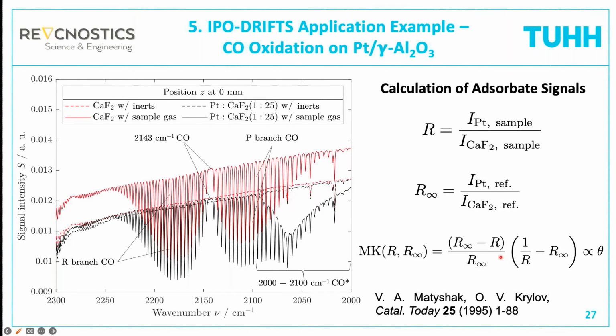And this leads then to this equation, and when you calculate this, you get a signal that is proportional to the surface coverage. We have tested this analysis with the pure Kubelka-Munk, which is most common, and it did not work as well. The Matyshak-Krylov was really better than the pure Kubelka-Munk function, and that's why we continued with this Matyshak-Krylov function. I gave you here the reference. This is a paper from two Russian scientists from 1995 in Catalysis Today. Well, thank you.